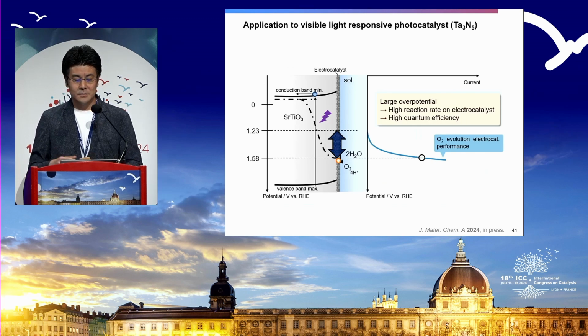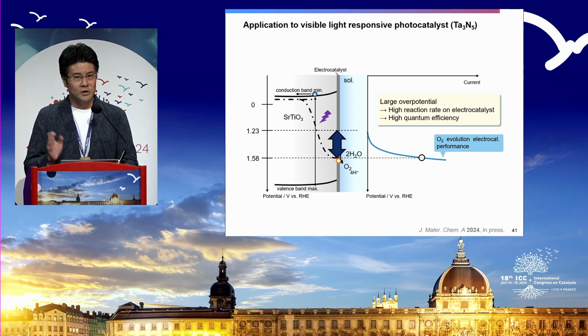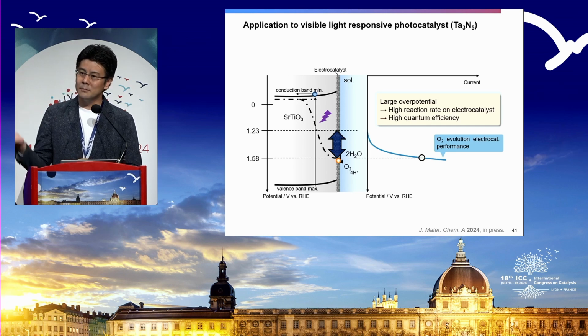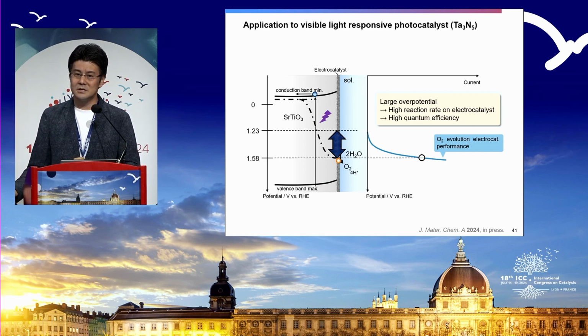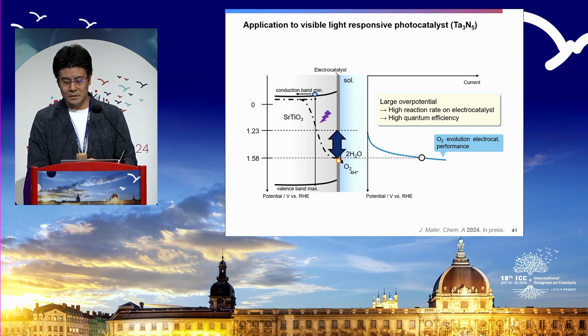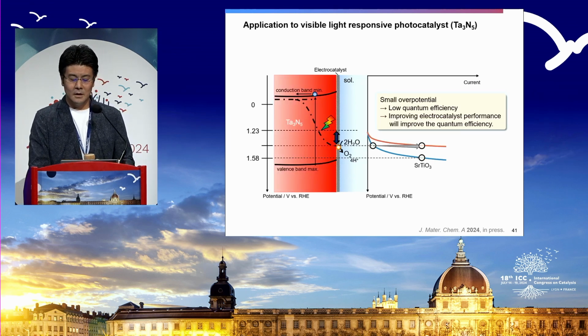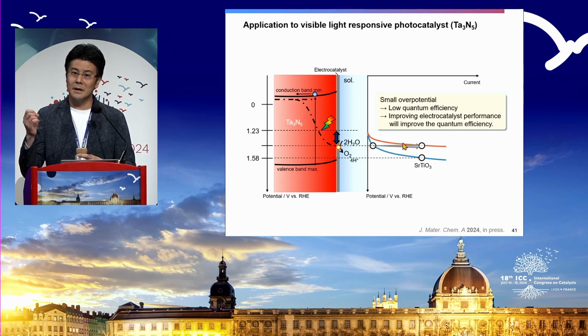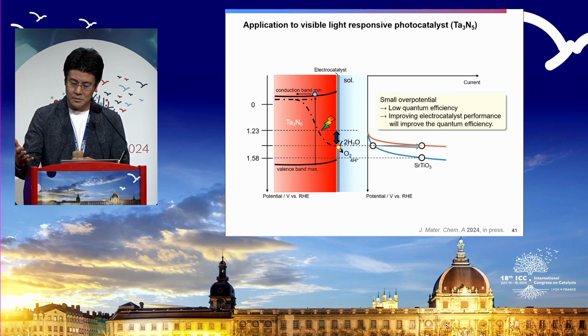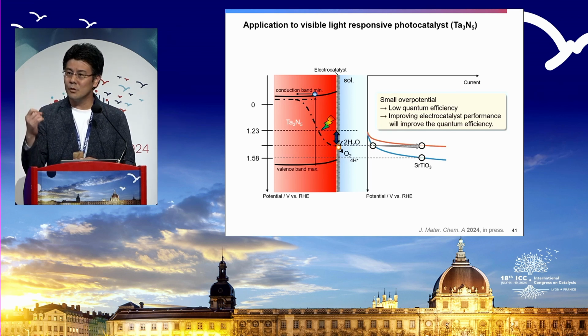So now I would like to finish by proposing a new type of morphology of photocatalysis. When you are working on strontium titanate, even if you have a bad oxygen evolution catalyst, because the valence band position is very deep, you can still drive oxygen evolution reactions. But of course, if you come to the visible light responsive material, like we're also working on tantalum nitride, you need to have a much better oxygen evolution catalyst, right? So the IV curve here should be much steeper. That means you need to put lots of catalysts. Lots of catalysts also makes the transparency lower. So we always have to think about how to design your oxygen evolution catalyst. You want to have more catalysts, but you don't want to lose transparency.